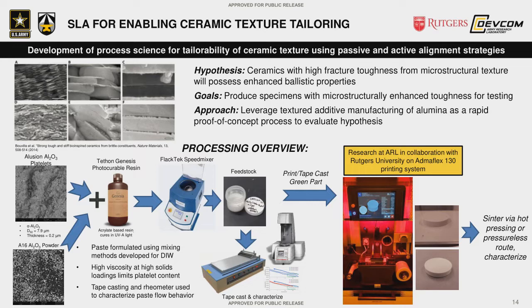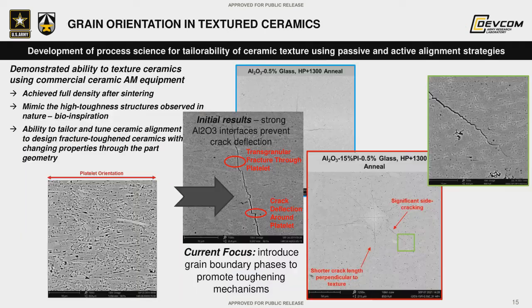We can then characterize its rheological properties and prototype tape cast it in-house using only small quantities before scaling it up to print the green part in collaboration with some of the folks up at Rutgers University who've been lending us their Admaflex 130 printing system, which is able to both shear align and print these parts. And finally, we sinter these via hot pressing or pressureless sintering, and characterize the microstructures and mechanical properties.